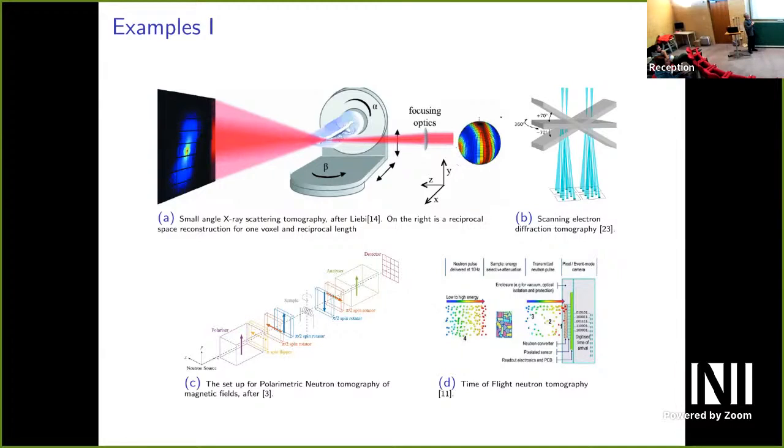What you do is you get a narrow beam of X-rays. You can make it monochromatic, one energy, and then for each projection, you raster scan the beam. So I like this sort of zero generation tomography that's given away. But for each of those beam positions, instead of just measuring what gets through, you measure a whole diffraction pattern. Right? That's why you need to raster scan the beam.